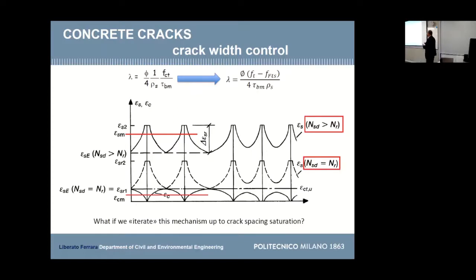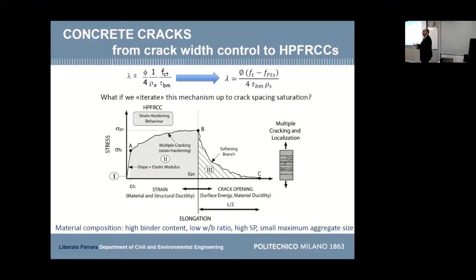So if we pick up the spacing of the cracks as a parameter, where is the effect of the fibers? Well, in the codes, you find that the effect of the fibers is here. This is the tensile strength of concrete. This is the residual post-cracking strength that the fiber reinforced concrete can guarantee you. So the fact that concrete can take some stresses even after cracking reduces the crack spacing, and then is beneficial further to the crack width. So if you iterate this process up to crack spacing saturation, you do not have any more space to form a crack. Here is the concept of ultra high performance concrete. You form the first crack at this point here.